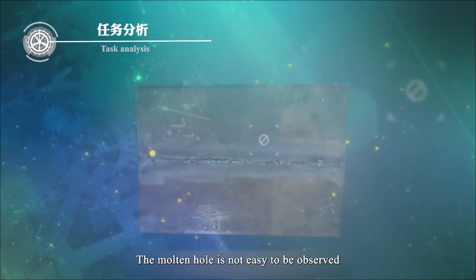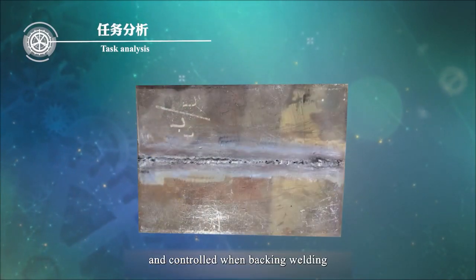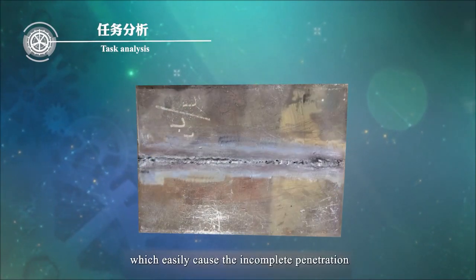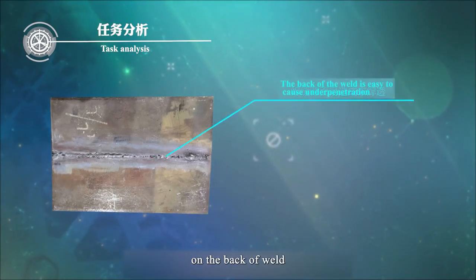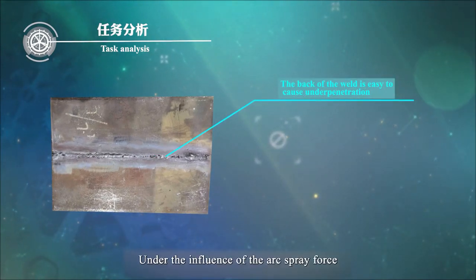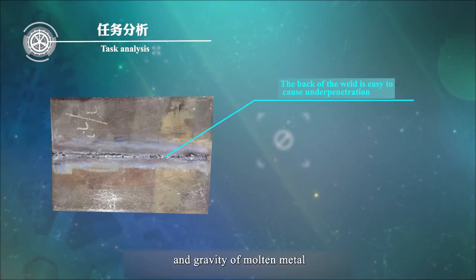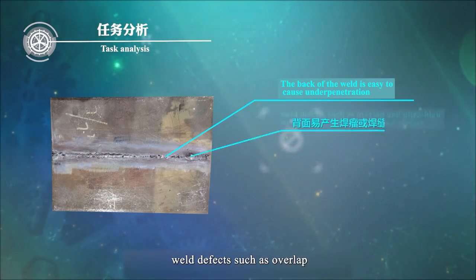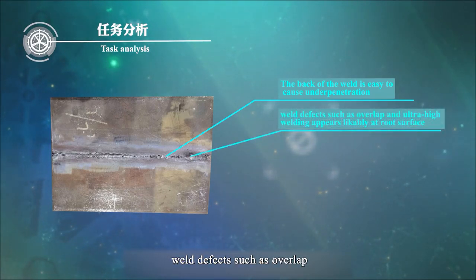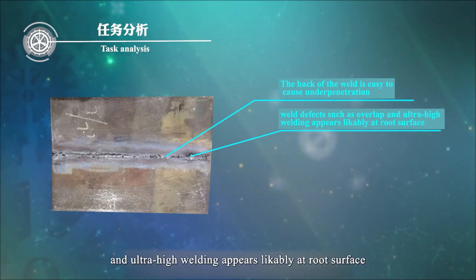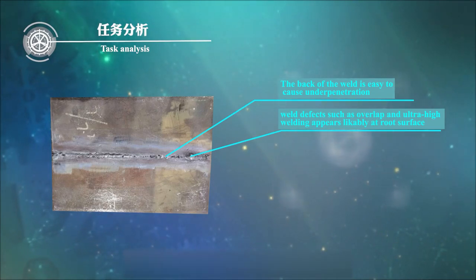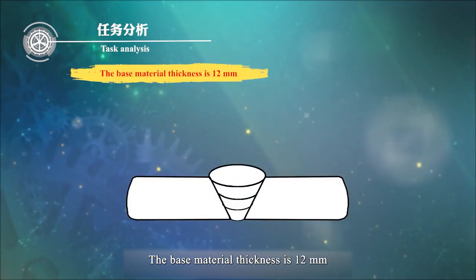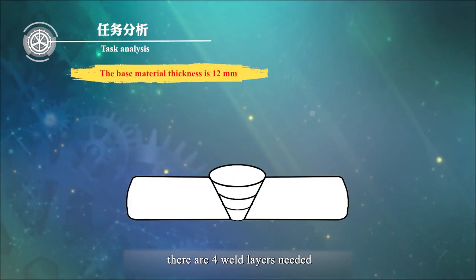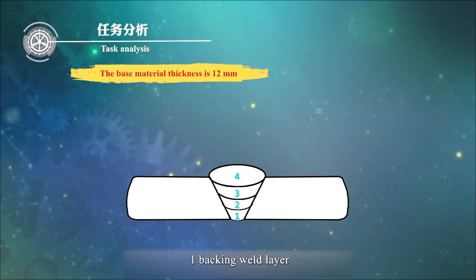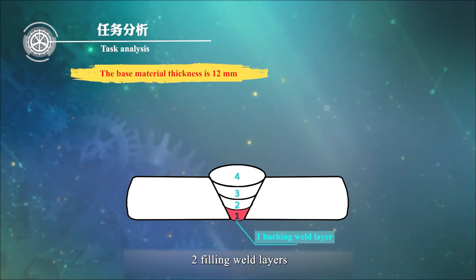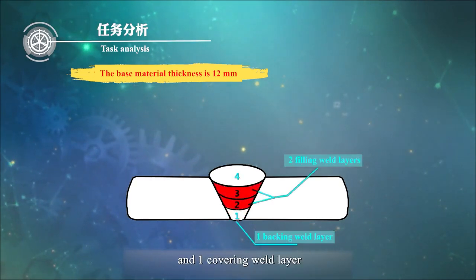The molten hole is not easy to be observed and controlled when backing welding, which easily causes incomplete penetration on the back of weld. Under the influence of the arc spray force and the gravity of molten metal, weld defects such as overlap and ultra-high welding appear likely at root surface. The base material thickness is 12 millimeters. Therefore, there are 4 weld layers needed: 1 backing weld layer, 2 filling weld layers, and 1 covering weld layer.